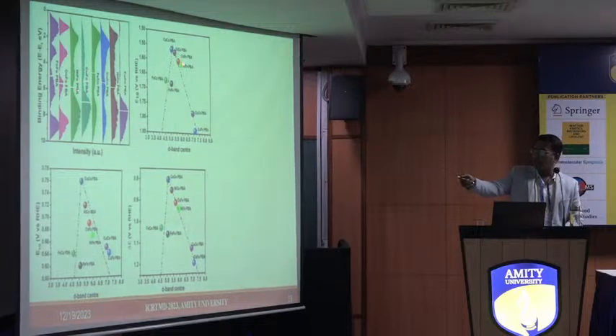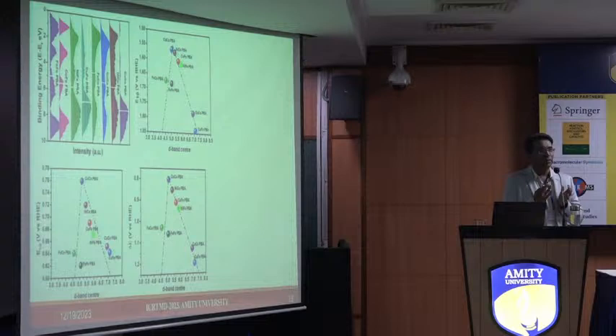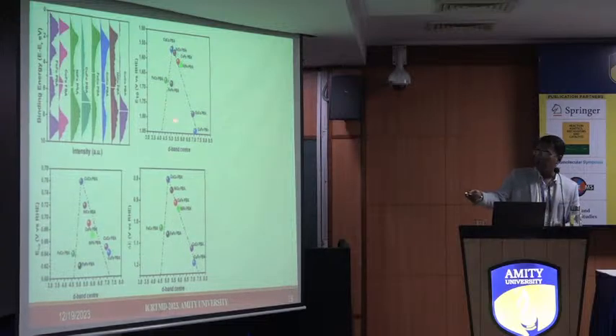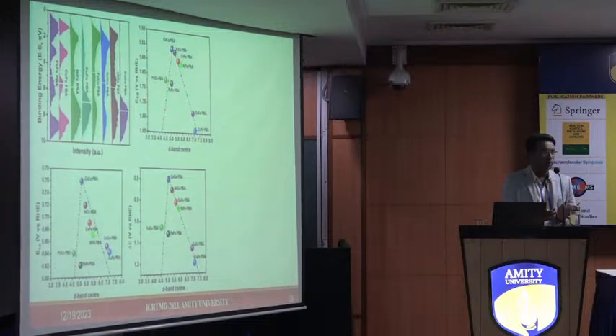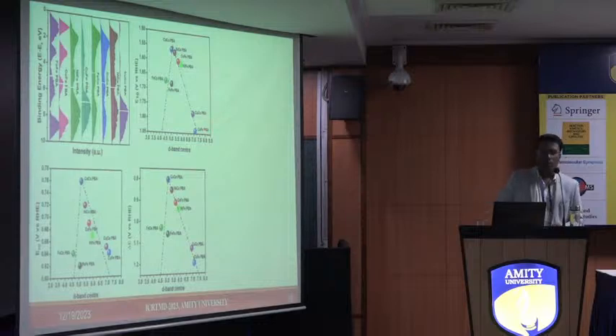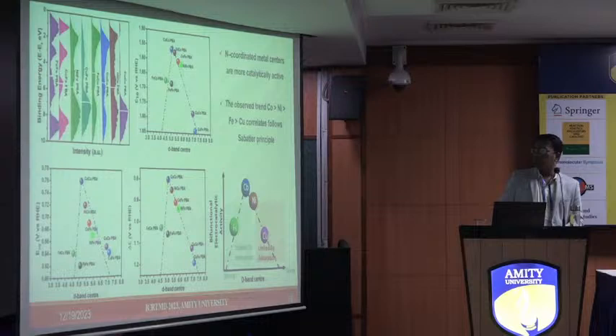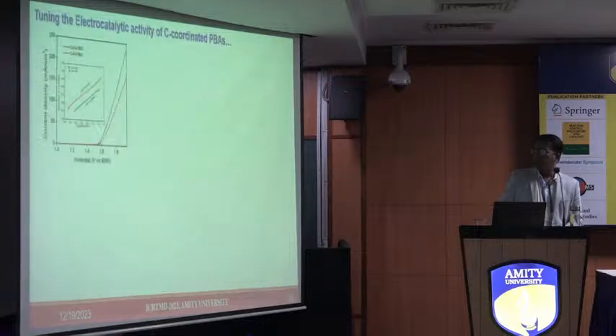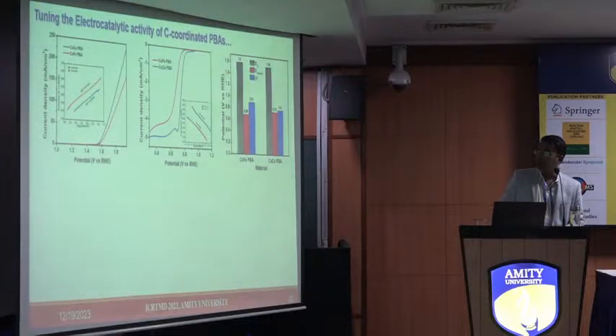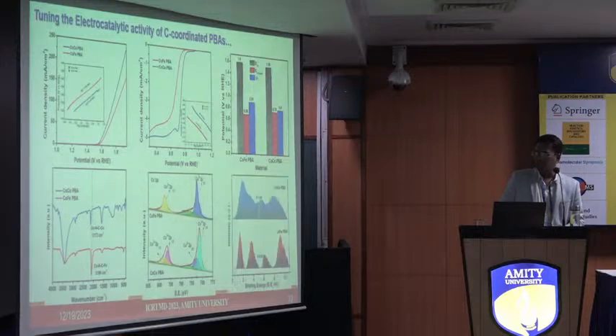Okay. On the left hand side, you have very less adsorption. So the left hand side is limited by the weaker adsorption. On the right hand side, you have the stronger adsorption of the reactants on the surface. So again, similar results we obtained for the carbon coordinated metal centers. Again, we can correlate this with the d band structure that we calculated.